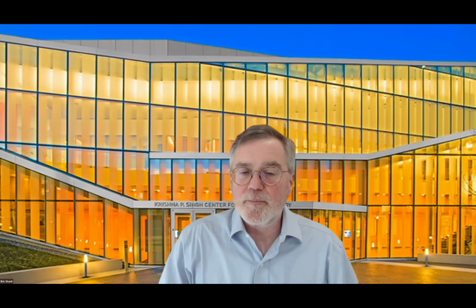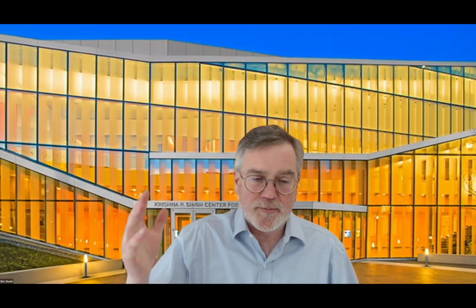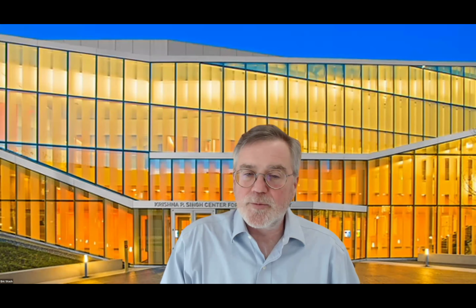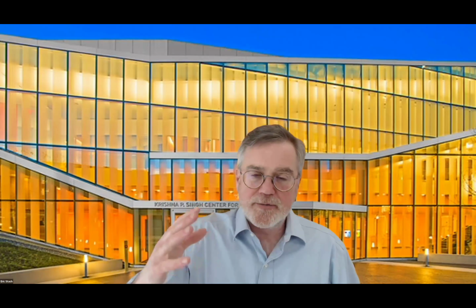Okay. Thanks. So Eric, for those people who don't have a synchrotron in their backyard and just have an electron microscope, how would they best do these experiments, in your estimation? So what I would say is that electron microscopy, because it has the ability to do imaging, diffraction, and spectroscopy, 2 types of spectroscopy, maybe even 3 with the X-ray if you consider it separate, is a pretty versatile tool for doing a lot of this stuff. I think the advantage to adding the X-rays on top of it is it tends to give you higher confidence in making statements that are from small statistics. It's hard to do tons and tons of electron energy loss spectroscopy because of the time it takes. And if you have the X-ray data, it gives you a sense that you're getting more information that's consistent across that.